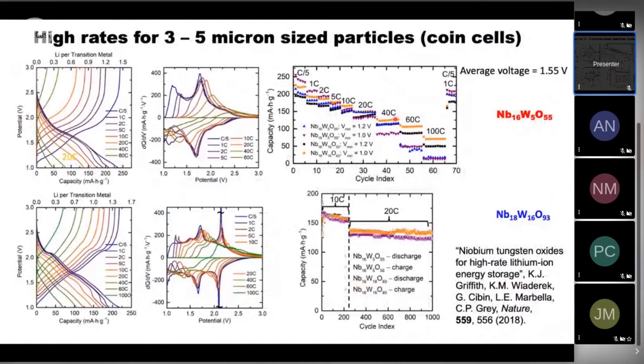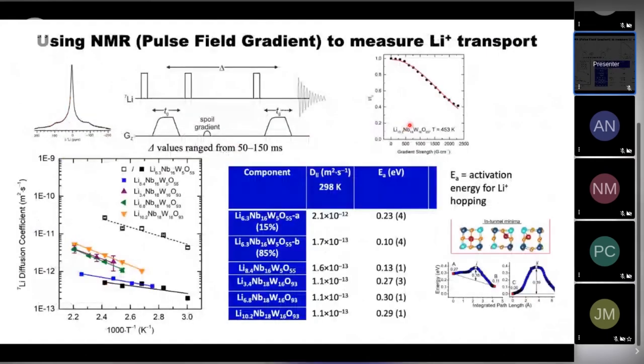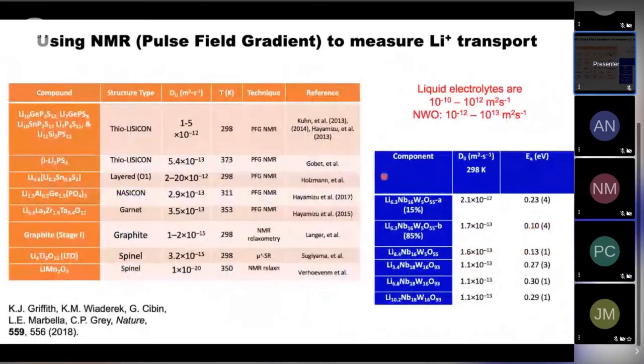And we can make batteries that we can cycle up to as fast as 1 minute charges and discharges. We can quantify how fast lithium ions move by using pulse field gradient measurements. And we can see that our materials are really as good as any lithium ion conducting materials.